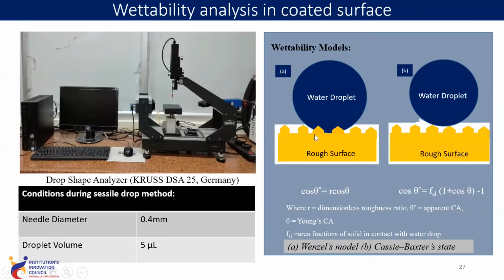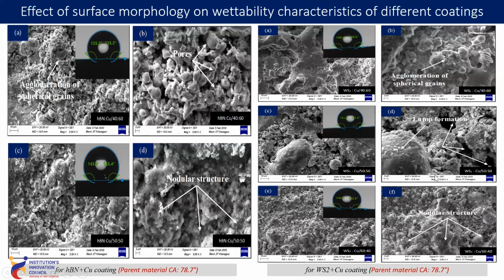The Cassie-Baxter model determines that if there is a large amount of porosity, then the water droplet will rest at the top of the surface. Otherwise, if it wets the surface, it will go through the rough surface. But here there is a nodular protrusion on the rough surface, which results in repelling the water, and a large contact angle is obtained. Basically, the parent material mild steel shows a contact angle of 78.7 degrees.